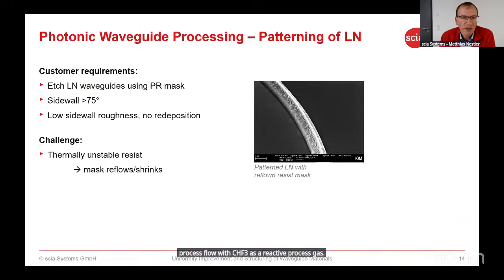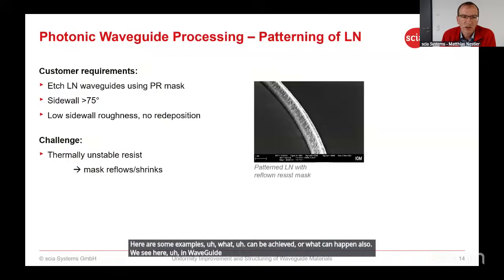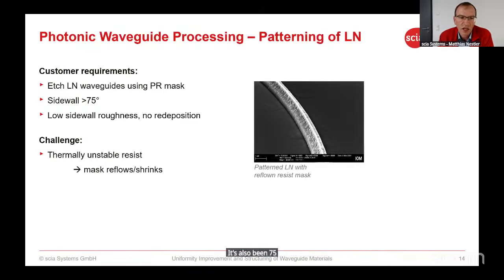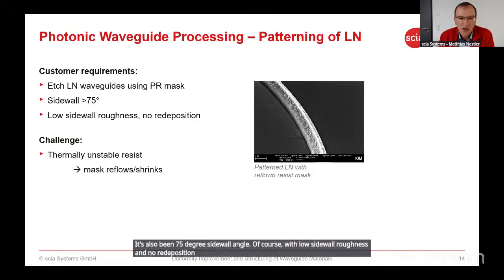Here are some examples of what can be achieved or what can happen also. We see here a waveguide that should be structured through a photoresist mask with a requirement of a sidewall angle larger than 75 degrees, of course with low sidewall roughness and no redeposition. But the challenge here was that the photoresist was thermally unstable, and so the mask reflows and shrinks. What you can see here in this SEM photograph is that the mask doesn't look pretty good.